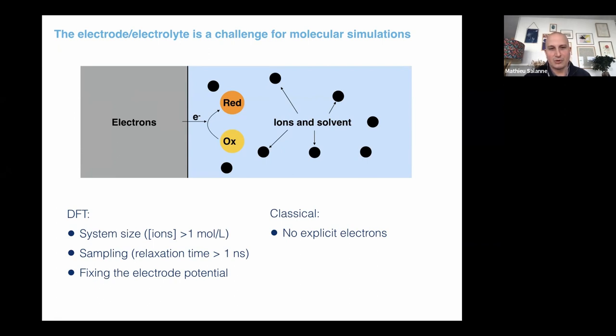DFT simulations are more and more used to simulate such systems, but the difficulty is that you have large concentrations of ions and long relaxation times, so typically adsorption times can be much longer than the nanosecond timescale. And also fixing the electrode potential is not so easy in DFT calculations. There are some new methods that are being developed, but for the moment it's not so easy. Of course, on the other side, the classical simulations are not very good at simulating electrons, but we saw in the previous talk that it's possible to have some tricks to manage this a little bit. And so I will show you a different approach, which is not data-driven, but trying to reproduce the physics of the system.